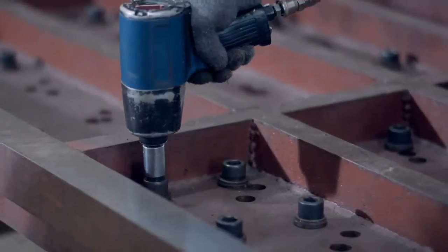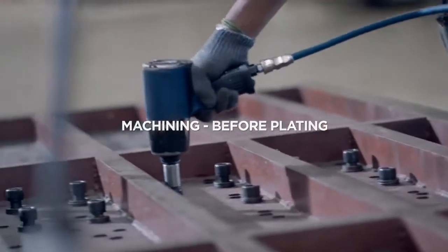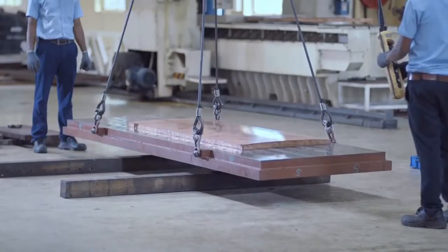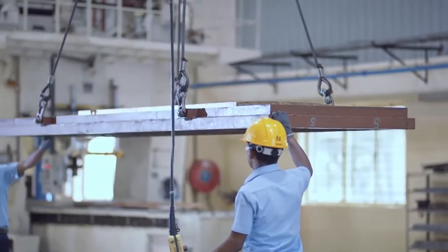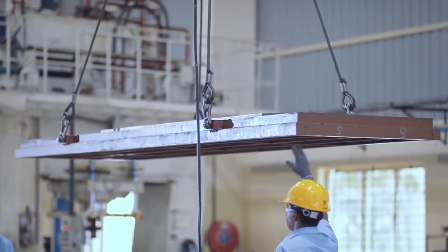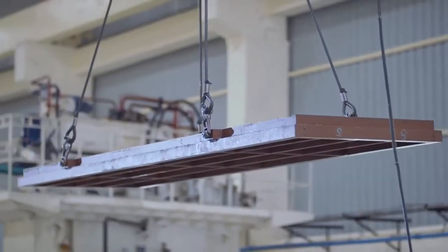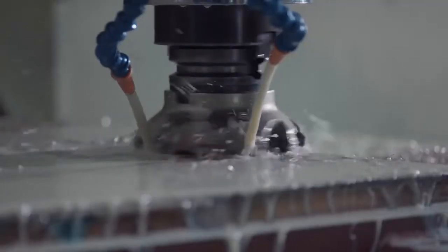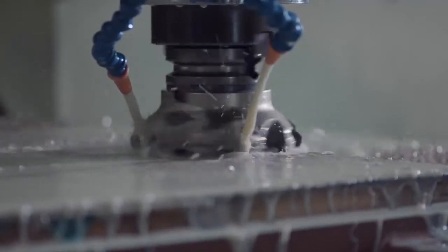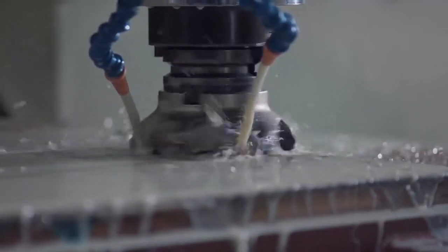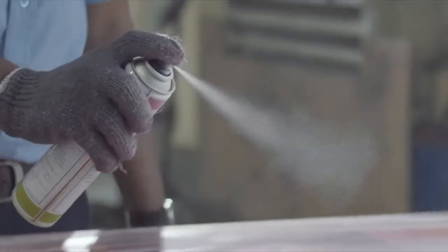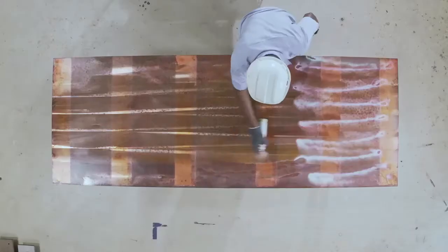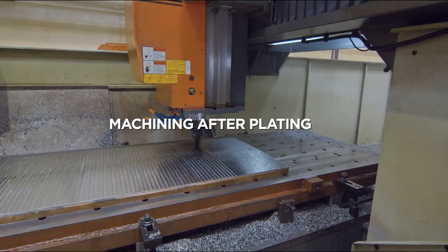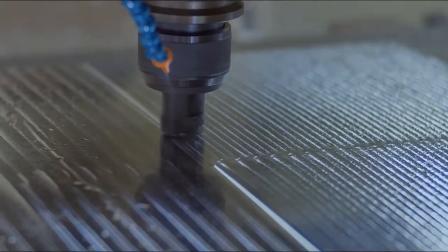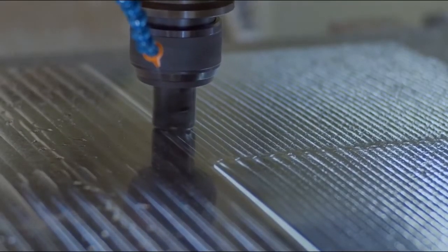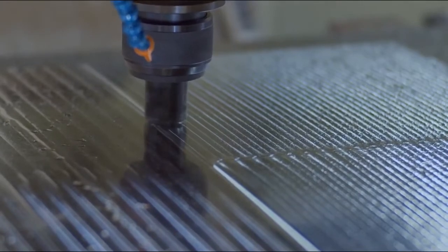The mold plates are assembled in the jig, loaded and indexed in the machine. The surface wear is then measured with dial gauge in the machine and recorded, and the mold plate is cleared of all the surface defects of wear, cracks, etc. A dye penetrant test is again carried out on the machine after plating. The mold plate is assembled in the jig and loaded in the machine for final machining.